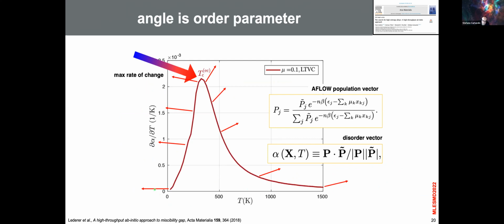If you go to zero temperature, you are promoting only a very well-defined number of configurations, two, three, depending on the convex hull. So this vector has a very well-defined direction in the space. Okay, just an arrow, right? This arrow. If you are at infinite temperature, all the states are equiprobable. That's SQS, right? So where there is nothing, there is no thermodynamics anymore. If every state is equiprobable, then the vector is going to point in another direction. It's the same vector, but it's a different direction.